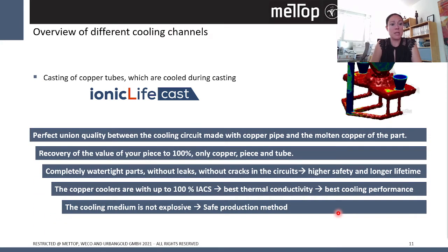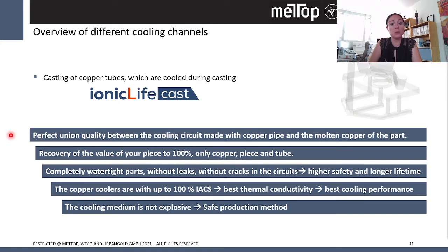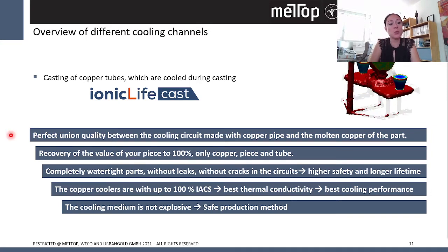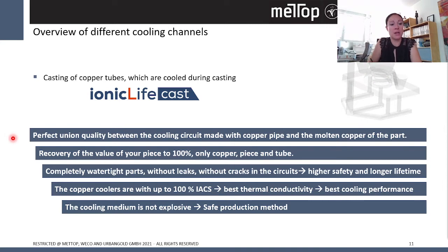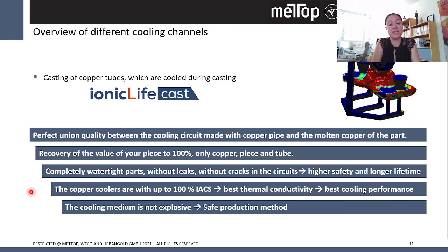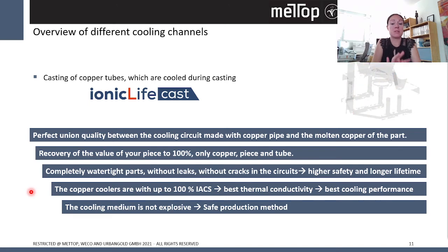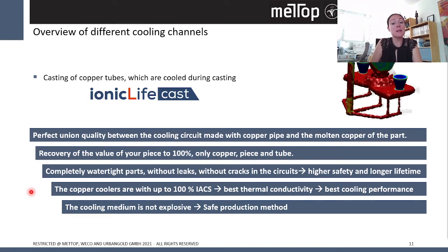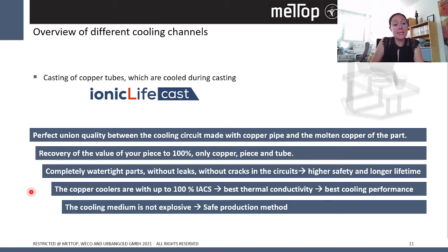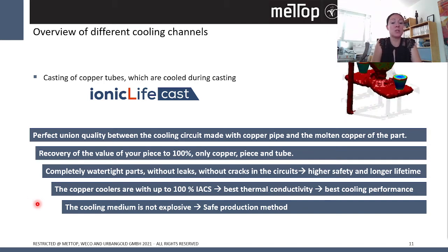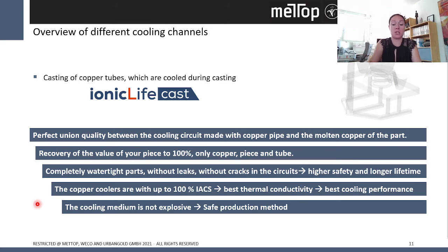So just to sum up, you have a perfect union between the cooling circuit and the copper matrix. You can recover the value of your copper to 100%. There is no nickel in it. It's just pure copper. And also you have the coolers with up to 100% IACS. So you have the best thermal conductivity, meaning best cooling performance. And since the ionic liquid as cooling medium is not explosive, you have a safe production method.